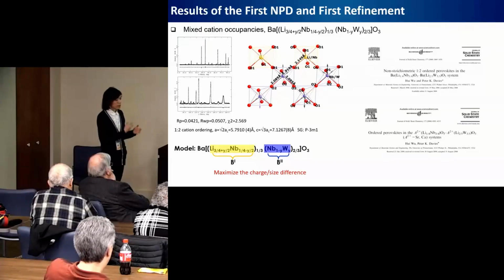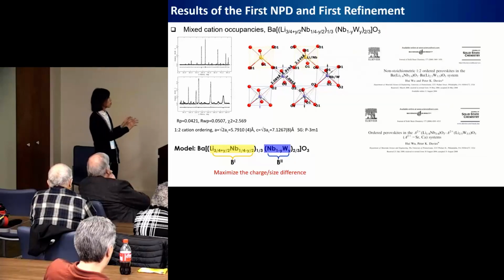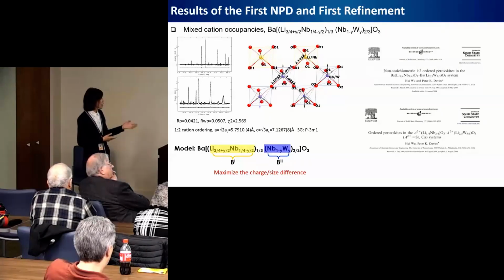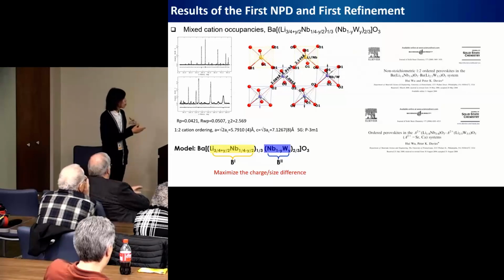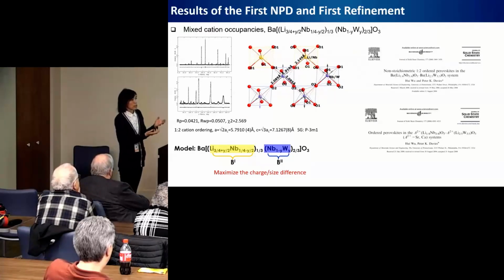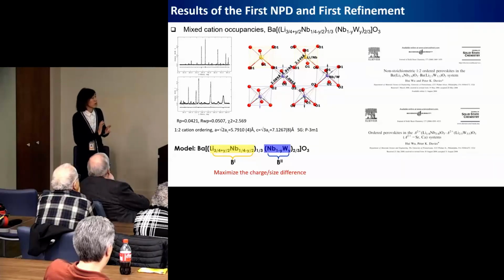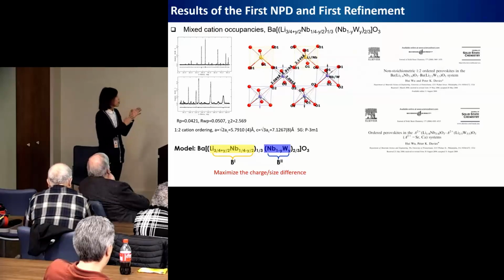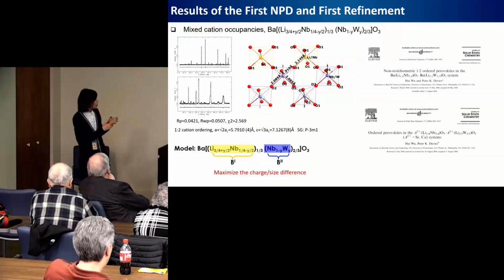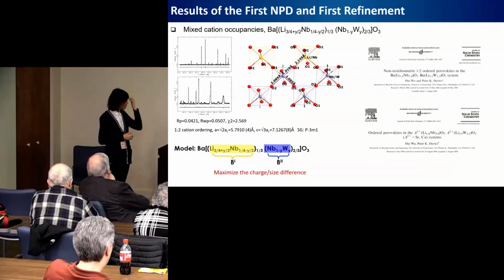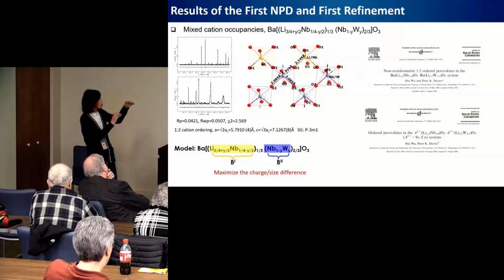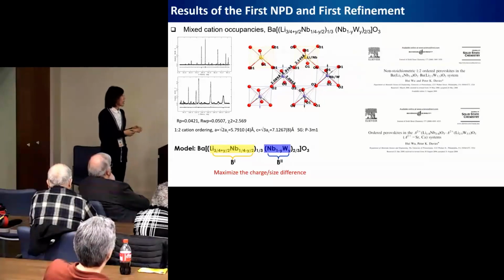Based on the neutron diffraction data, we finally confirmed our hypothesized model. Niobium is distributed on both sites, which maximizes the charge and size difference between the two B-site cations and promotes cation ordering. We also determined the position of oxygen, and we indeed observed some BO6 octahedral distortion, which elongates the B2-O bond length and alleviates the overbonded oxygen. That's the oxygen between the two smaller and more highly charged B-site cations.